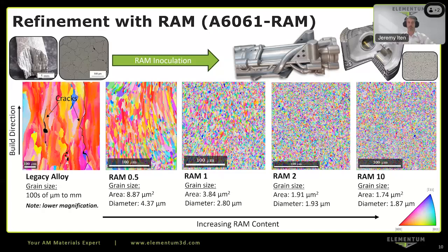Thank you. Okay, next question. Do you find a significant decrease in ductility as you increase the RAM percentage? Yeah, so as you go up to higher ceramic volumes, that is the trade-off between like a RAM 2 and a RAM 10. Depending on the starting material, you might still have very good ductility at RAM 10. But if you're starting with a less ductile material, as you do increase the ceramic percentages, you do tend to lose some of that ductility because you're really getting a combination of the ceramic and metal properties.